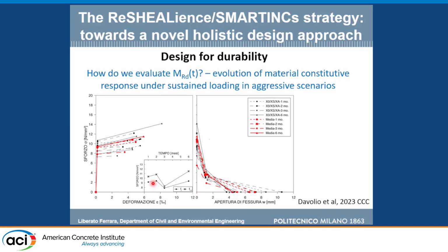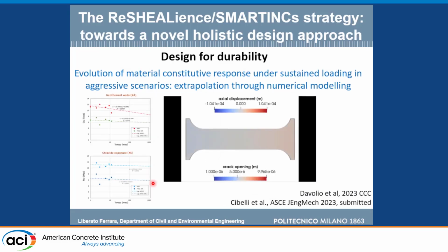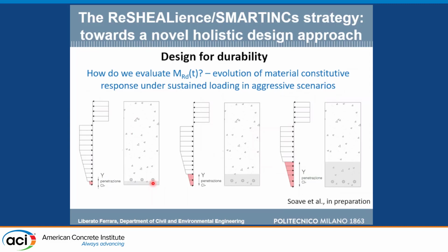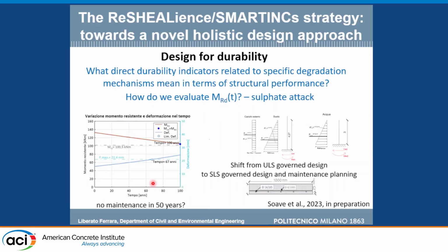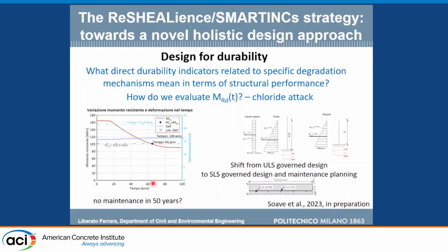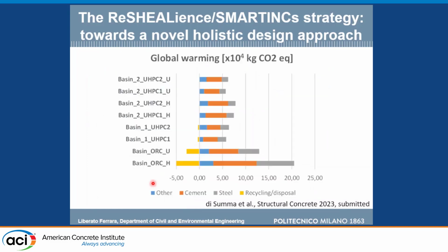So we identified this time-evolving constitutive law of the materials. Obviously, we performed tests up to 1 year. You cannot go longer. Students have to graduate at a certain point. You have to allow them to finish. So we validated with numerical models to extrapolate this to the whole service life of the structure. What we simply did is, when we computed the cross-sectional equilibrium for axial force and moment, we used time-evolving constitutive laws. And we ended up estimating, you can see here, a service life longer than 100 years when we used our UHPC with nanomaterials. This is the case of the cantilever wall, and this is the case of the slab wall.